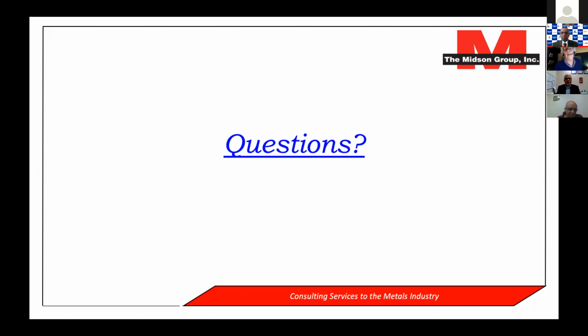Well, that's a training issue, I think. People have to be trained to not just go in there and start being very aggressive with the die, because they will remove the coatings. People have to be trained to be more gentle with the die. And it should be easy to use anyway, because soldering should be reduced and erosion should be reduced. But you do have to be a bit more careful, because as I said, they are pretty thin, and you will go in and remove them if you're not careful.